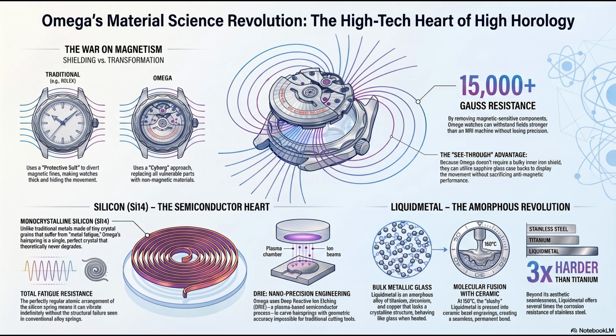Okay, Cerachrom. Yeah, and this is not the ceramic of a coffee mug. We are talking about advanced industrial ceramics, typically synthesized from zirconium dioxide or alumina. And the manufacturing process for this is just wild. The source says they take this microscopic ceramic powder, inject it into a mold under immense pressure, and then sinter it. Right, sintering. Which is essentially baking it at roughly 1500 degrees Celsius. And during that sintering phase, the ceramic physically shrinks by about 25%. 25%, that's a huge shrinkage.